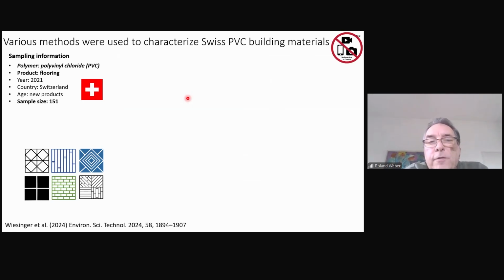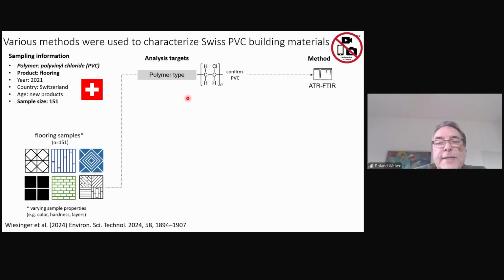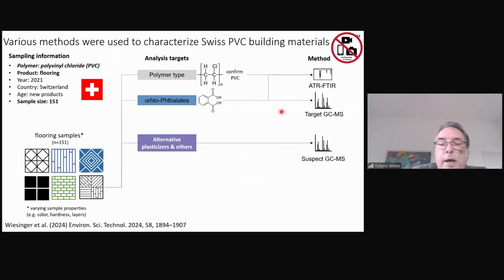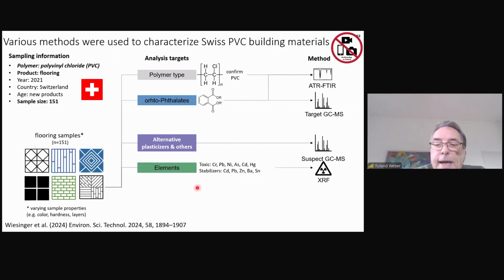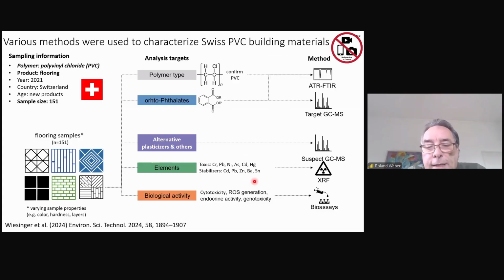Here, a best practice study from monitoring of additives in PVC in Switzerland. They analyzed 151 flooring samples. They determined the polymer type, and only for PVC they were looking. They looked for the phthalates. A range of the phthalates are restricted by REACH regulation. They also analyzed what alternative plasticizers are in, and they analyzed elements like cadmium and lead, which were frequently used as additives in PVC in the past. And they also did biomonitoring for toxicity of extracts of these